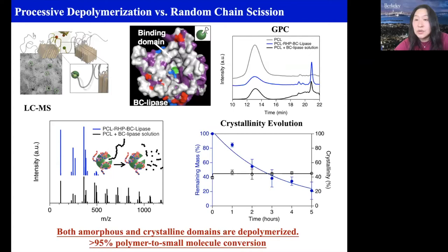When we also start looking at the small molecules, the degradation byproducts, this is where we did LCMS, and the blue corresponds to this deep pocket embedded enzyme inside of the plastic. And you know, it's not like we get all monomers, we also get dimer and trimer, but they are all small molecules, and they can be either degraded or metabolized by the microbes nearby in the compost facility, or you can collect them. In fact, we collected the degradation product and repolymerized it. And the process can be recycled several times. It really closed the loop for the plastic.